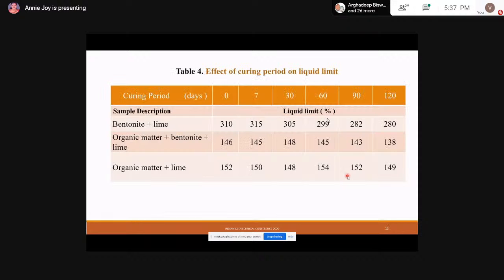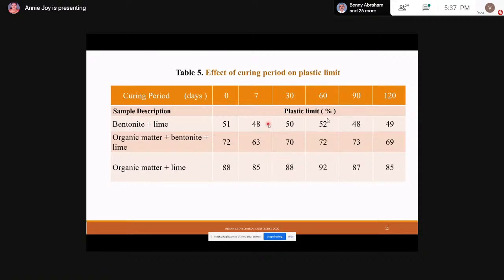Coming to the results and discussion, first is the effect of curing period on the liquid limit. From the table, you could see that for the bentonite plus lime soil mixture, the liquid limit went on decreasing with the increase in curing period. But when you consider the organic matter, with increase in organic matter, the liquid limit goes on increasing. The same trend was observed for the plastic limit also.